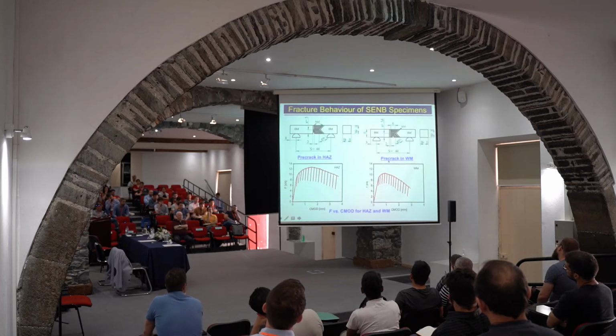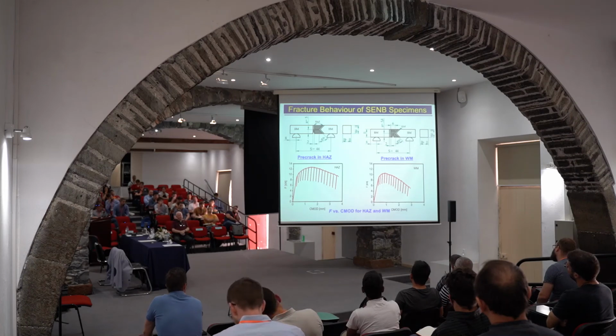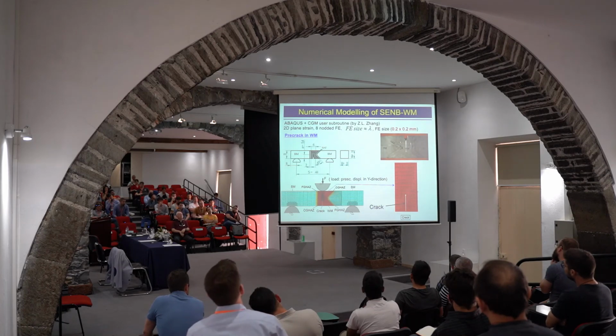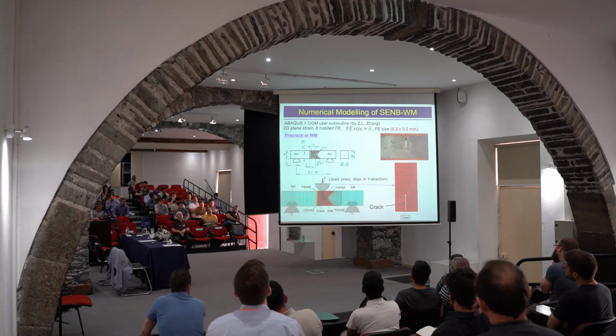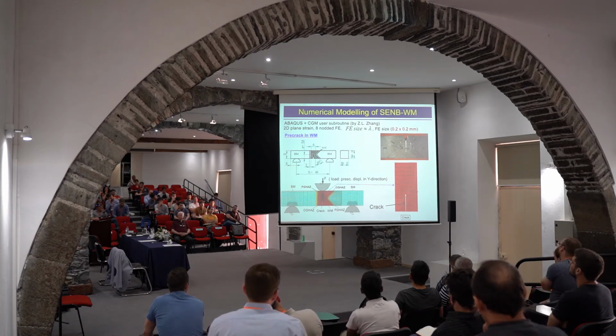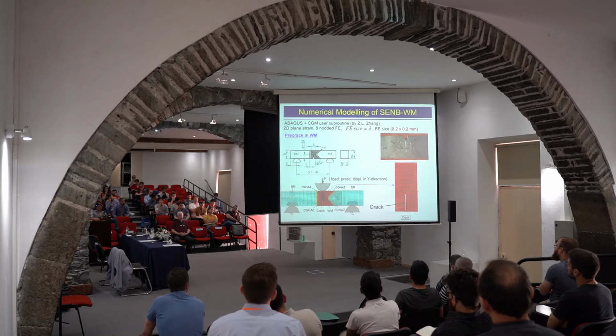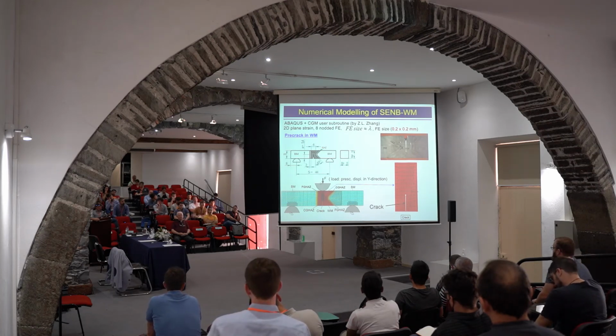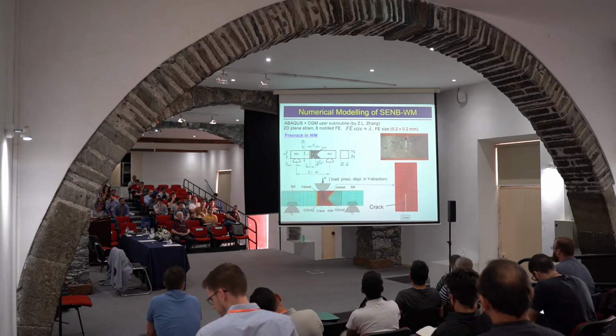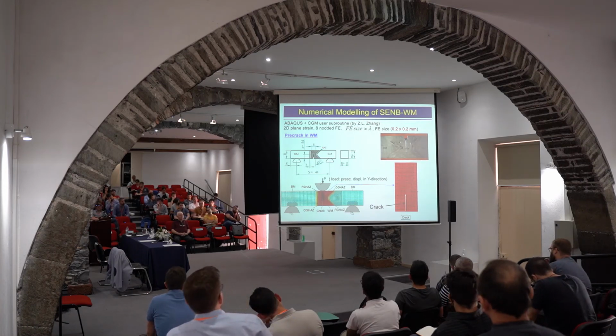After that was done, we could test both 3-point bending specimens and weld metal in two ways. Sorry, actually we tested the 3-point bending specimens and tensile panels, and then we numerically modeled them, of course. That's the point here. But 3-point bending specimens were simulated in 2D analysis, and tensile panels were simulated in a 3D model. So that makes yet another difference. That was done intentionally to find out how it works in both cases.